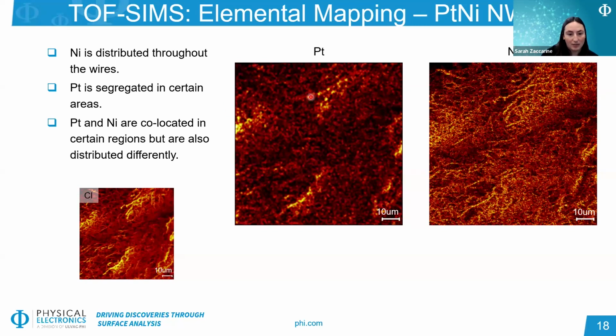We do see that it looks like platinum is appearing brighter in certain areas, and if we look back at the chlorine map that I showed you on the previous slide, we see some corresponding bright spots. So it might be that these were more in focus in these wires, but generally the platinum we see a little bit tracking with that wire structure. It's just a fairly low signal.